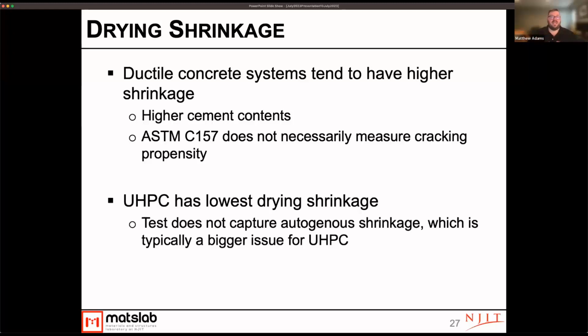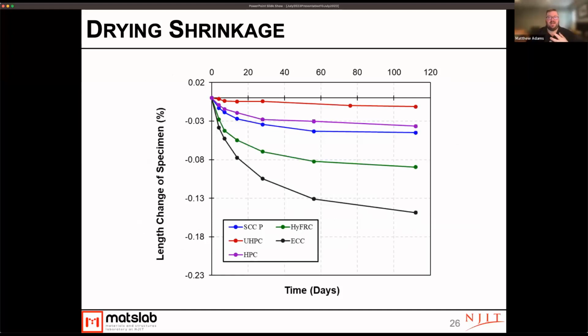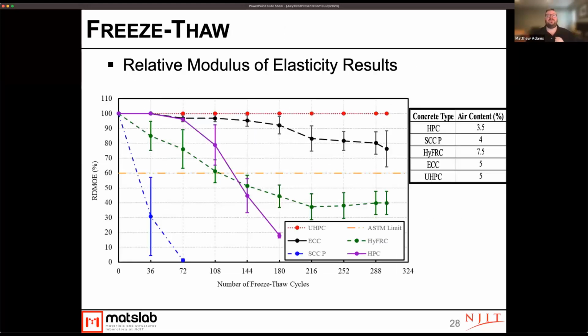And that really needs to be captured earlier on. And this test method really allows those systems to cure for too long to capture that autogenous shrinkage. And so, basically what we can say is that the shrinkage results were probably in the same area for these systems, and probably around the same cracking propensity. But of course, when you use those fibers, you'll hold everything together, so you could get less ingress.